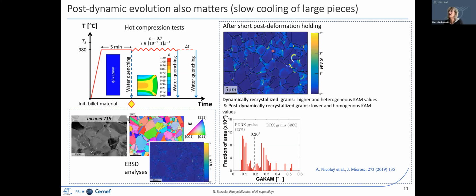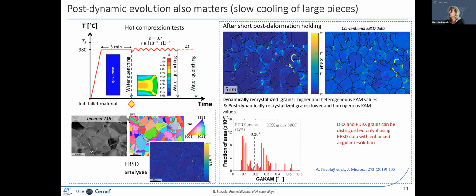So actually they are a little bit work hardened. And others have grown after deformation during the holding time, and those ones have much lower internal misorientation levels. If you're using such high angular resolution EBSD data, you can recognize these two kinds of grains. But if you just use, I would say, conventional EBSD data with an orientation accuracy in the range of 0.5 degrees, then you would not be able to separate the two kinds of recrystallized grains.